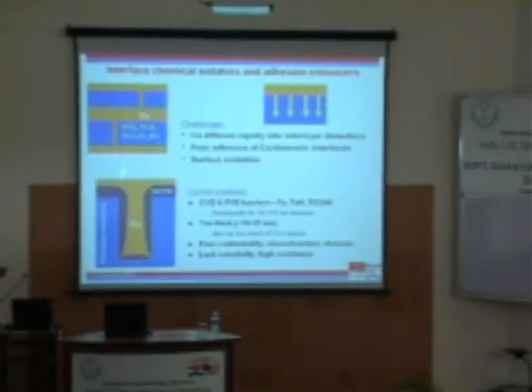This will cease to be a nano device if I need to put a micro layer in between to isolate it, or even let's say this dimension is of the order of 45 nanometers, and the diffusion barrier layer that I need to put in is going to be 10 nanometers, that is a large amount. So I'm compromising the area that I need for low resistivity copper. So ideally, I'd like to have this as thin as possible. The diffusion barrier should be as thin as possible to isolate as well as provide integrity.